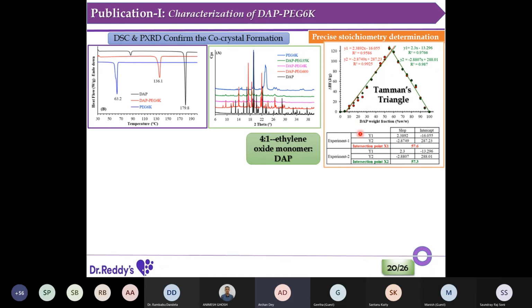So we use DSC as a tool. We make binary mixtures again and construct what is called a Tammann's triangle, and the intercept of the dapsone weight fraction with the enthalpy gives the idea about the precise stoichiometry. If we convert that weight stoichiometry to the molecular stoichiometry, we got 4:1 ethylene oxide monomers, so one dapsone per four monomers.